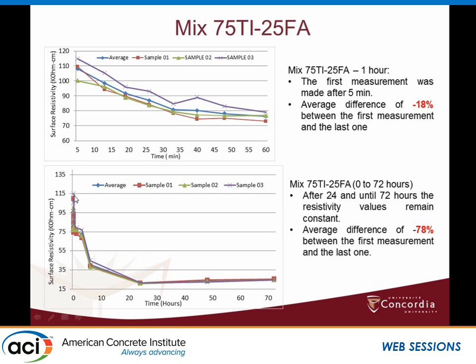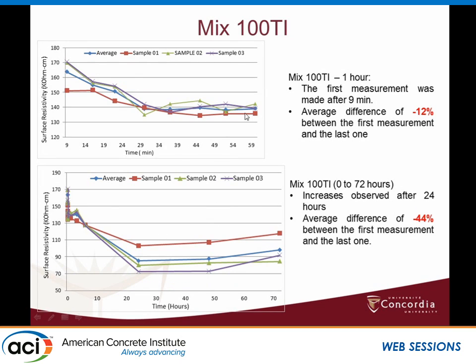Also, the complete test was 72 hours, and you can see this line represents the first hour, and until 72 hours, you can see that after 24 hours, you obtain almost a constant behavior. This is quite similar with the other mix, the old sample. The first hour had a decrease of 12%. And when you look at the old test graphic, you can see that after 24 hours,